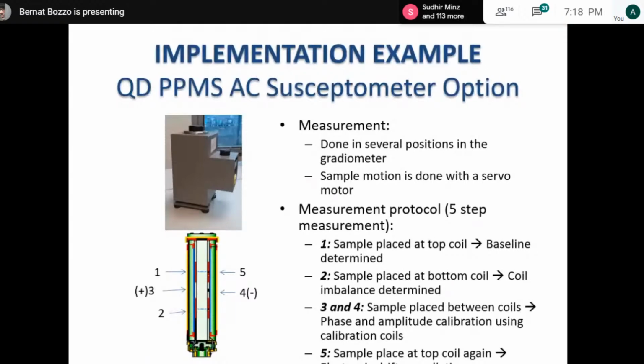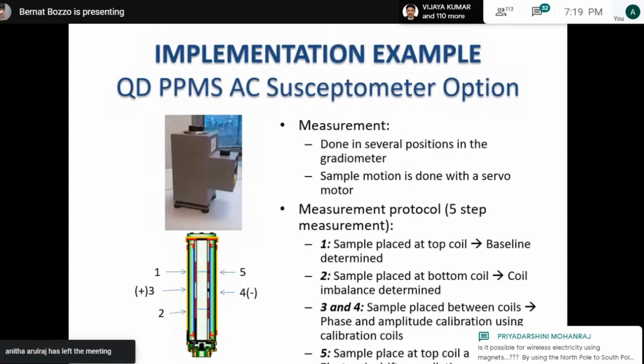Then, with the sample at the center of the coil system, we calibrate the amplitude and the phase using a known fake magnetization signal. Finally, we place the sample at the top coil and repeat the phase measurements. With this, we reject the field drift in this long measurement.